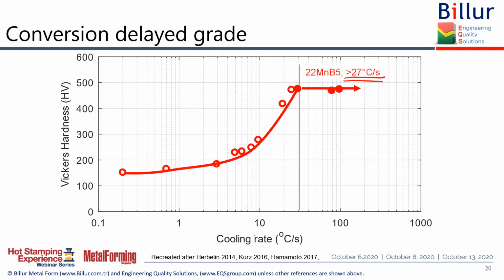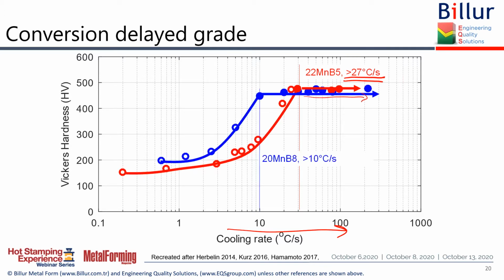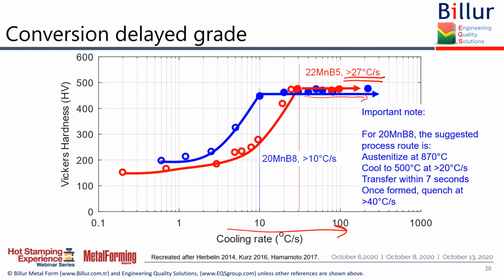This is, by the way, logarithmic. This scale is logarithmic, as you can see. If I can cool it more than 27 Celsius per second, I have almost always the same hardness. For 20 MnB8, this number goes down to 10 Celsius per second. But the typical process route is to austenitize it at 870, cool to 500 at over 20 Celsius per second, transfer within 7 seconds, and once formed, quench it at over 40 Celsius per second.